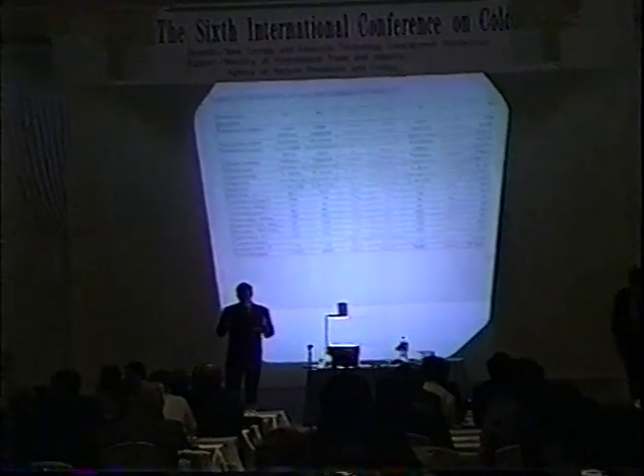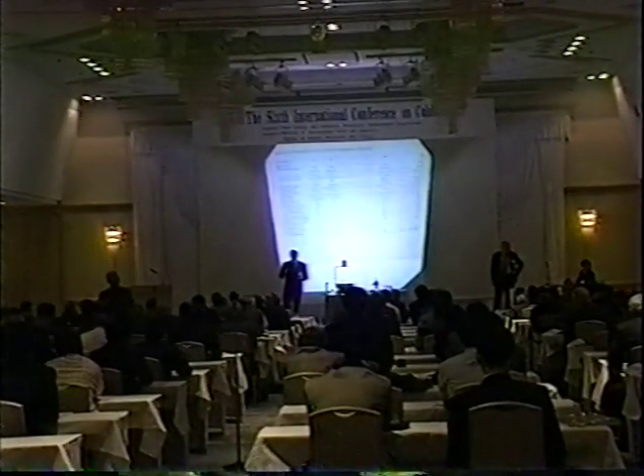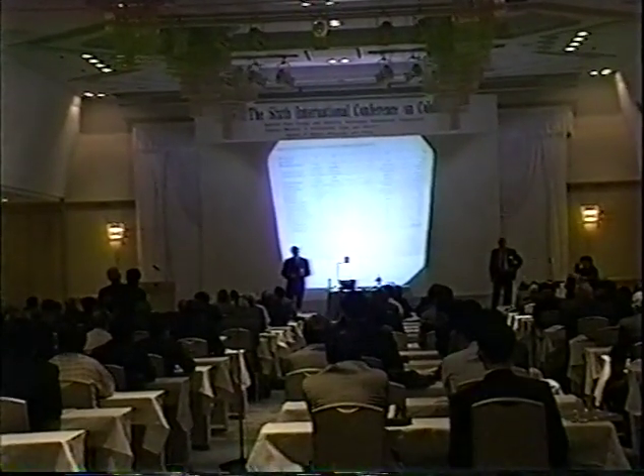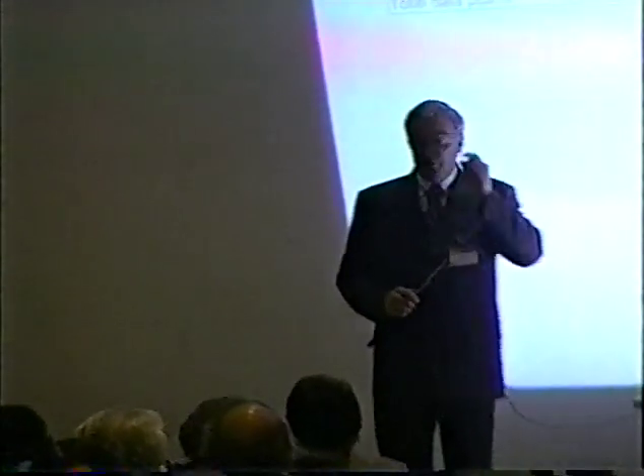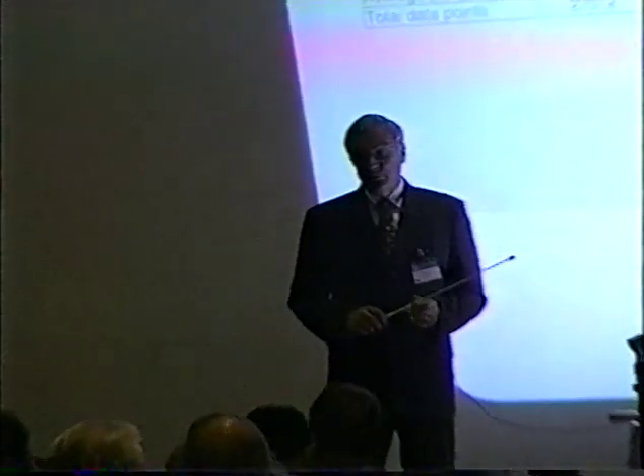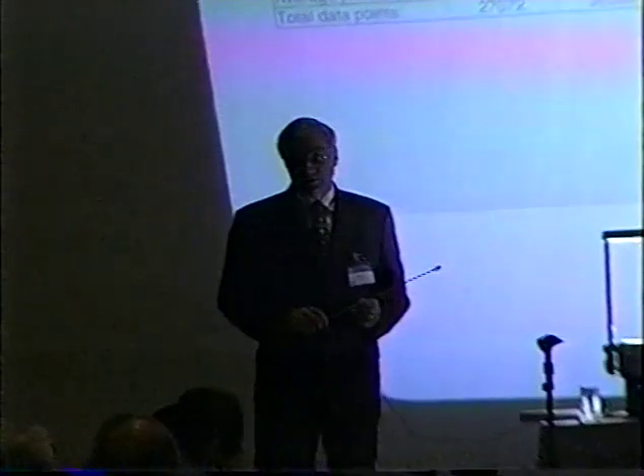Do you find any variation of the calibration depending on the spatial distribution of power generation? With the spatial distribution of power generation? Suppose, in other words, the calibrating heater is in different places. You let it come to thermal equilibrium. The time constant now is down to around 3 hours, so you may get any effect you like in the first 3 hours, but after that 3-hour period, you see nothing but flat input power, flat temperature. And it really goes where the heater is with respect to the axis of the calorimeter? I'm very sure it would be. So we always keep the electrodes in the heater exactly where the calibration was. We've not done a systematic investigation of that. Certainly we have enough blank experiments, or experiments which have shown no excess, to substantiate that statement.